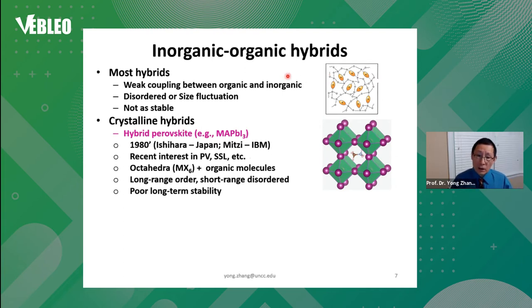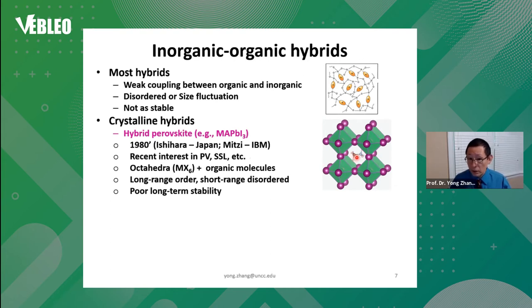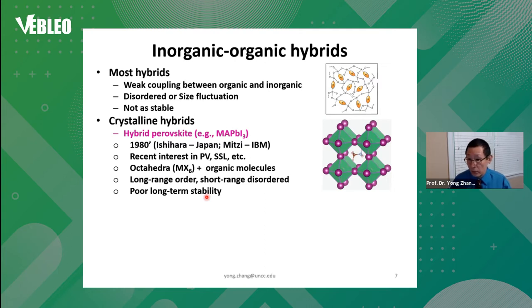However, there are two issues with hybrid perovskite. One is it's not a perfectly ordered structure: you have a cage-like unit repeating in space, but the molecule inside this cage is randomly oriented — so you do not have short range order, although you have long range order. The other major issue is this kind of material is not very stable; you can have it for at most a few months before it degrades.